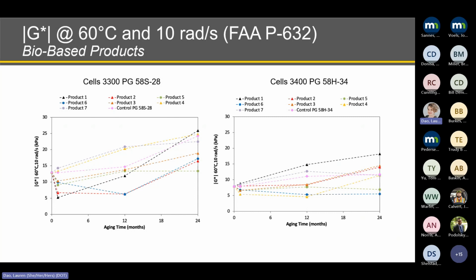We can also see that, specifically considering the PG 58S-28 binders, even though we have a significant decrease in stiffness after 1 month of application, as time progresses, these treatments start to be differentiated, and not necessarily the treatment that has the highest softening after 1 month of application is the one that remains having the lowest stiffness after 24 months of field aging.